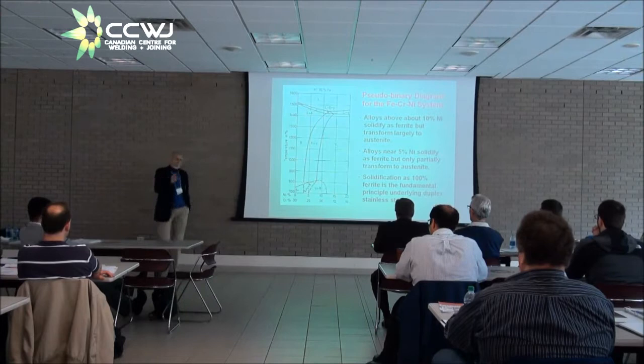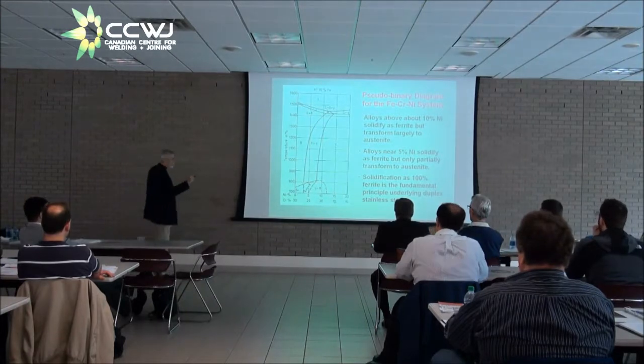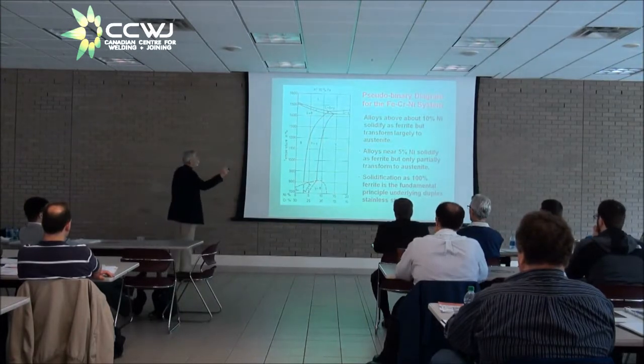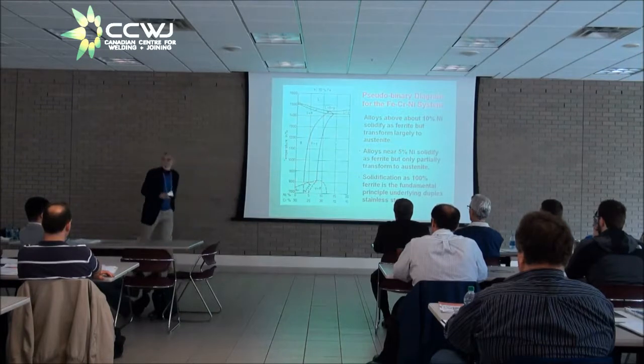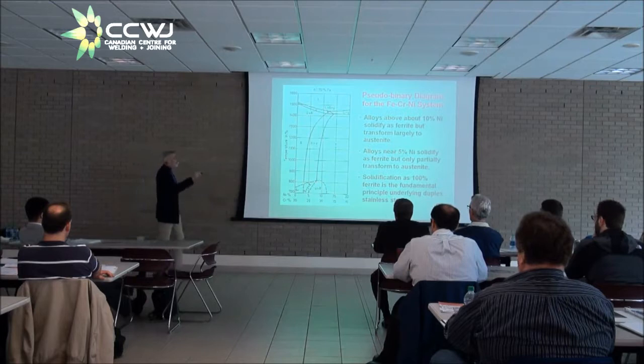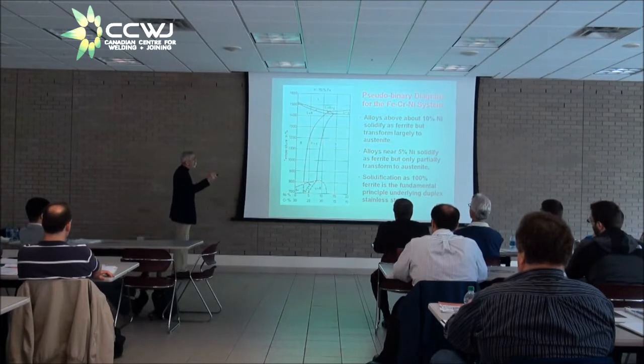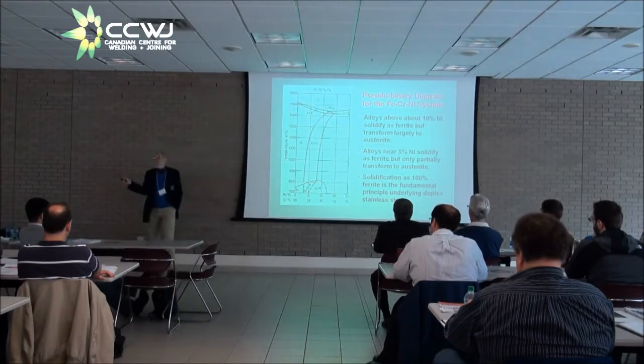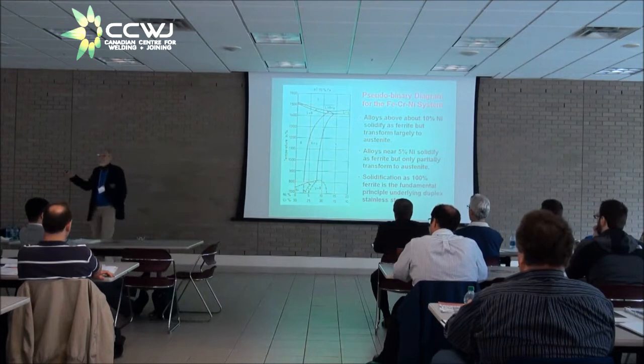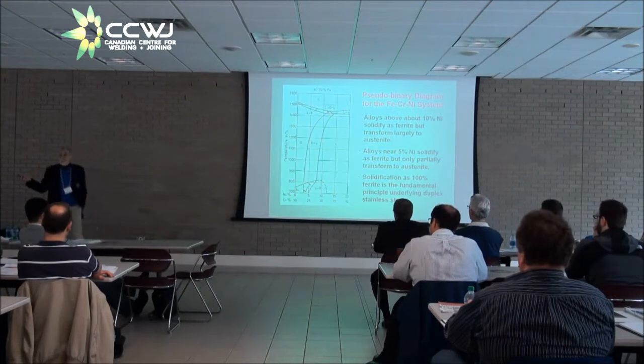All right, now a duplex stainless steel starts out further to the left in the diagram, someplace over here, where its solidification goes from liquid to liquid plus ferrite to 100% ferrite. And 100% ferrite exists for an appreciable temperature range. Then as you cool further, it enters the two-phase field where ferrite and austenite coexist. That ferrite plus austenite will coexist until the cooling has gone so far that nothing else happens. And that's what you freeze in at room temperature.